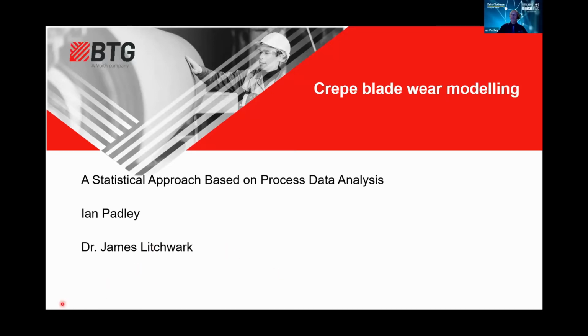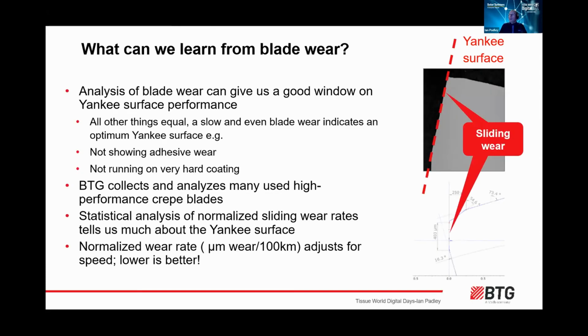As I was saying, we were going to take a look at some of the material Franz was talking about. What can we learn from the blade wear? Analysing the blade wear gives us a good window on the Yankee surface. We want the wear to be slow and even. In this way, we know we're not getting adhesive wear against the Yankee, which can eventually cause Yankee damage. And we also know that we're not running on very hard coating. So if you like, we need to be in the Goldilocks zone, not too hard, not too soft on the coating. And looking at the blade wear can tell us a lot about that.